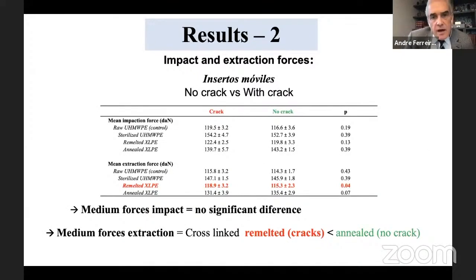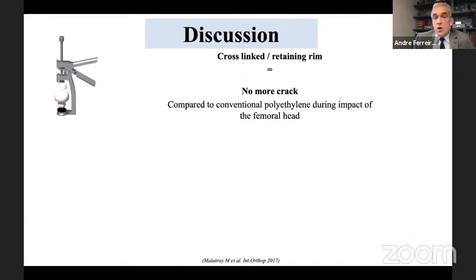And then after the impact, they extract the head from the insert and compare the force used for that, and of course the cracks. There was no significant difference of the median force used to impact or to extract the head from the insert. But with a median extraction force, with the remelted cross-link, they saw more cracks than with the annealed one. So we can only say that with cross-link and retaining rim, there is no more cracking compared to conventional polyethylene during the impact of the femoral head.